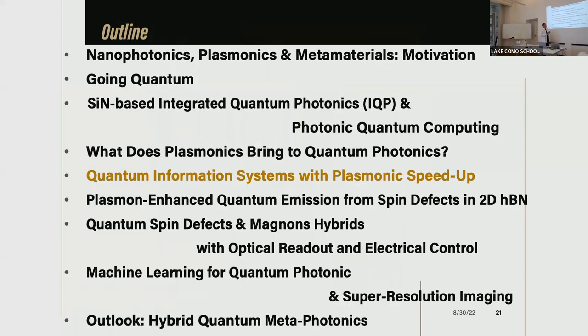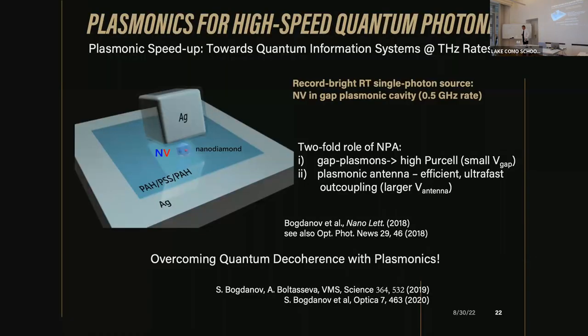That's the straightforward idea. So let me give you some examples and some preliminary results. I should say right away, we're not there yet. But what I will show clearly indicates that we should eventually be there, and hopefully sooner rather than later. So we use so-called nanopatch antennas. That's actually very important. You cannot use a simple plasmonic particle. If you use a small plasmonic particle, yes, you have very strong confinement, but the emission of photons is proportional to the volume. If your particle is, let's say, 10 nanometers in size, it doesn't emit much. You basically confine energy within this particle, and eventually it doesn't have any other way but to go to ohmic losses. So it's not good.